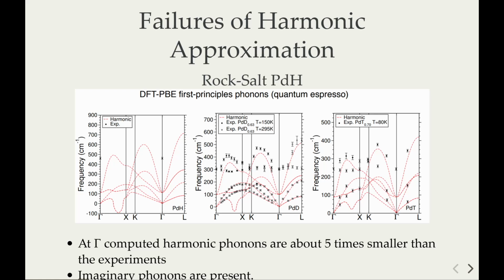This is a strongly anharmonic material, where you can see the harmonic theory fails dramatically. If you plot, for example, the dispersion computed from harmonic phonons, you immediately see two big problems. The first is that there is something like a charge density wave, an acoustic phonon mode that becomes imaginary in a very small region, and this is a signature of instability of the structure.